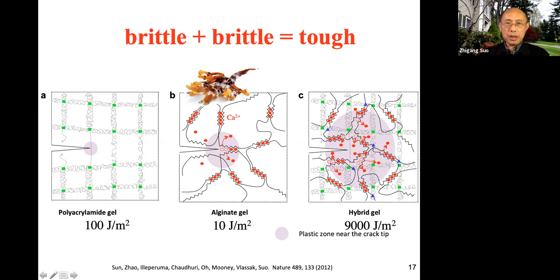And we have another hydrogel. It's coming from seaweed, a biopolymer. You have one chain here, another chain here. In the natural state, it's cross-linked by ions, calcium, because on the chain you have some negative charge. Calcium ions have positive charge, they zip up. This alginate, it's called alginate, comes from a kind of algae. It's kind of like tofu. So when a crack comes along, you need to unzip here, but you do not need to unzip off the crack plane. As a result, you only unzip one plane of calcium cross-links. That gives you 10 joule per meter squared. Again, this is a measured number. We don't compute this, we just measure it.